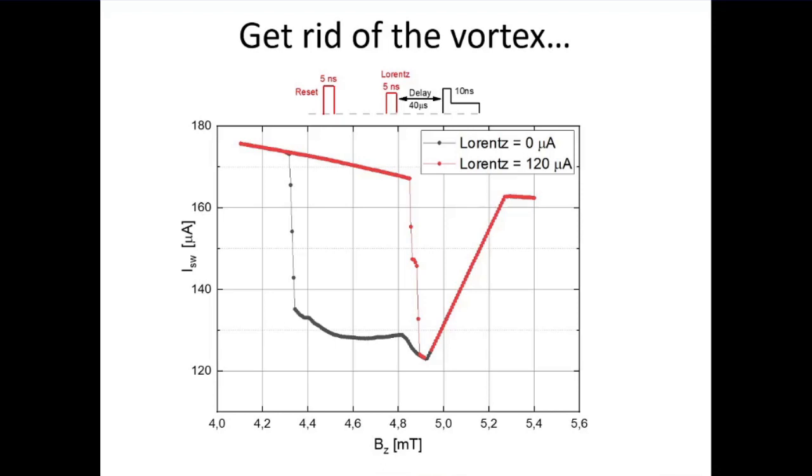Here we have a vortex, and when reading out the bridge, we expel it, we heat it, and that is why the critical current is lowered. Here we don't have a vortex, so when we probe the bridge, there is nothing to be expelled, so we don't heat. And this is a rather huge difference in the critical currents of these two configurations, with vortex and without vortex.